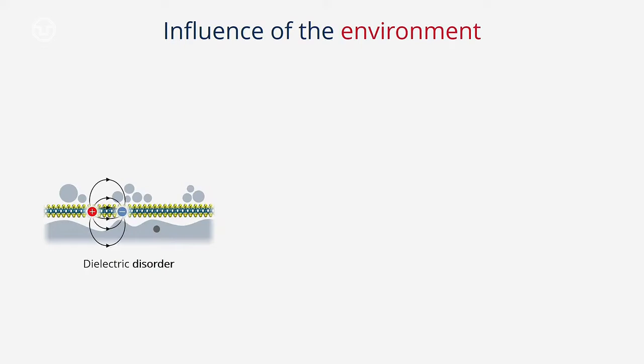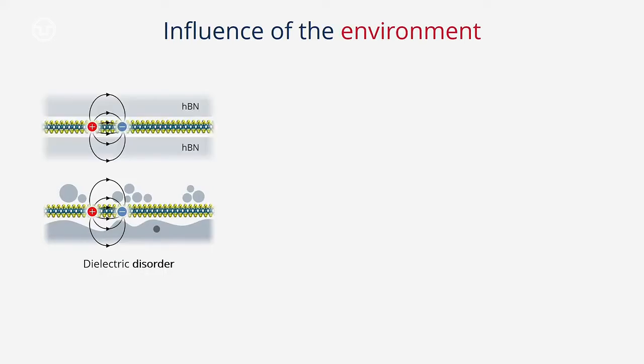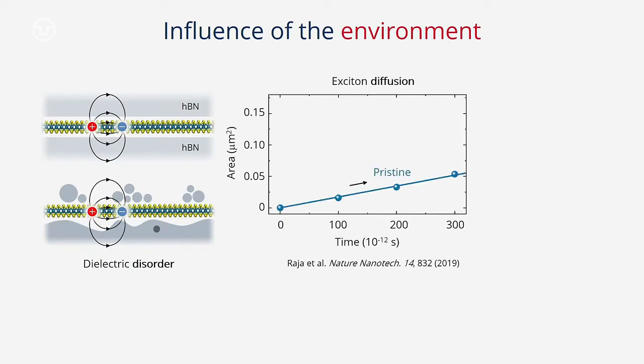It's often detrimental. But if we understand how it happens, why we have disorder, we can also get rid of it. And in this case, what we do, we encapsulate this material in also extremely thin crystals. So we create a sandwich, protect it. And then if we look at the properties of such a system, what we see is that in a pristine sample, we have some propagation. So excitons move somehow, fine. But if we encapsulate it, we get rid of disorder, then the transport becomes extremely fast.